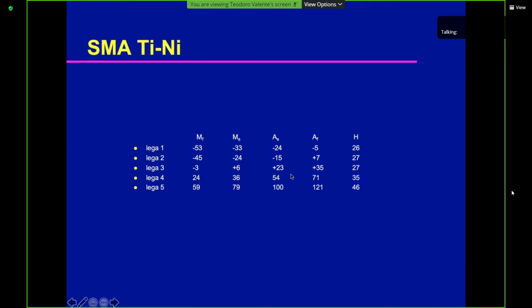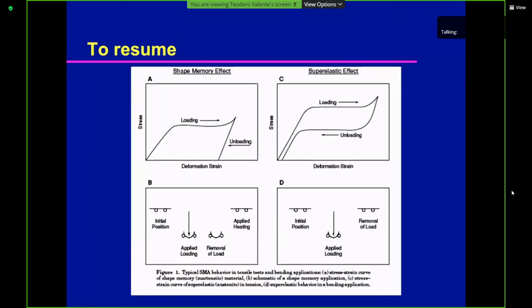And then we can achieve the full formation of austenite again from the formed martensite when we reach the high temperature value, which is, in this case, around 70 Celsius. That is a temperature value which can be easily managed in an industrial way, and thus we have available nitinol materials which can be processed by using the shape memory behavior they can exhibit without any particular difficulties.